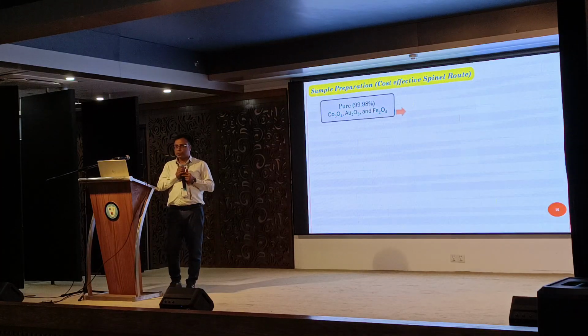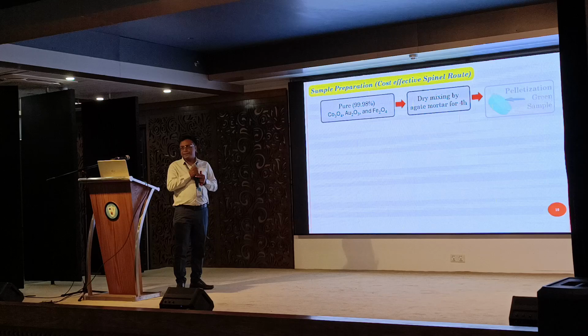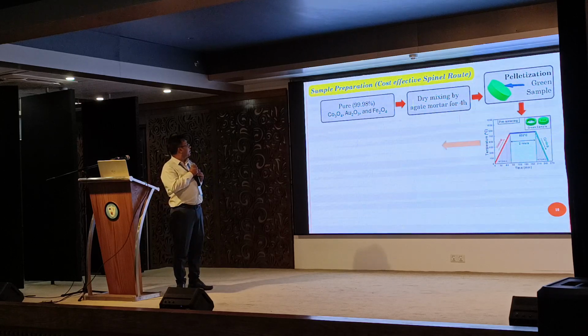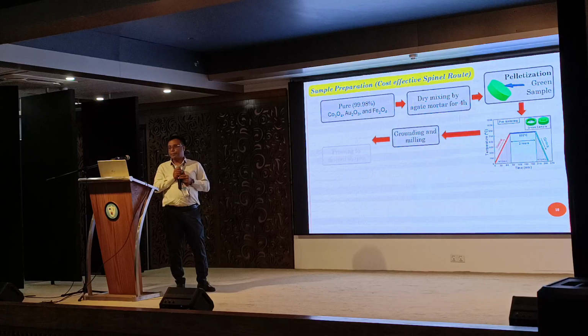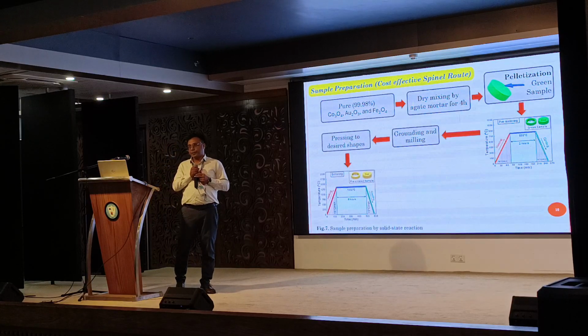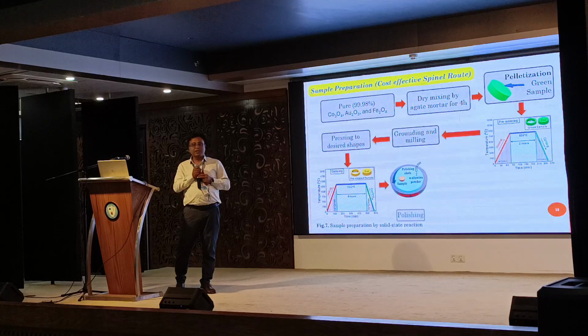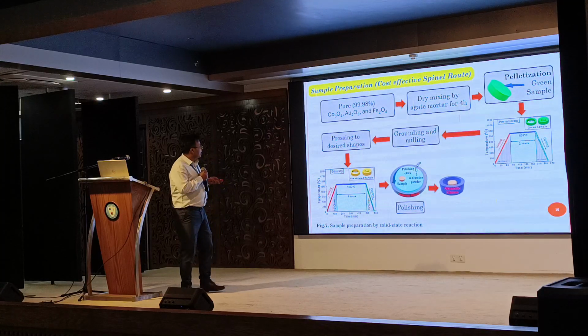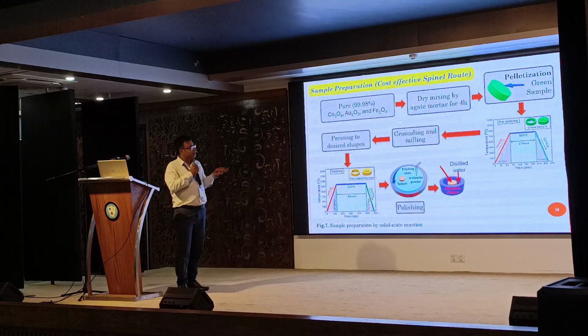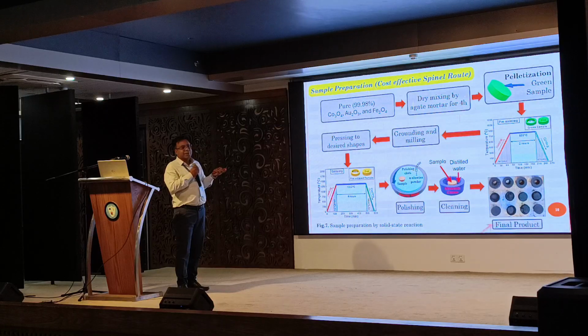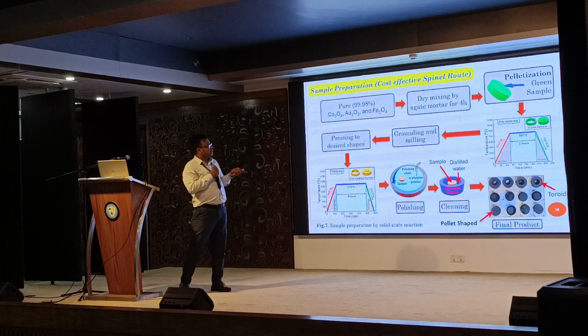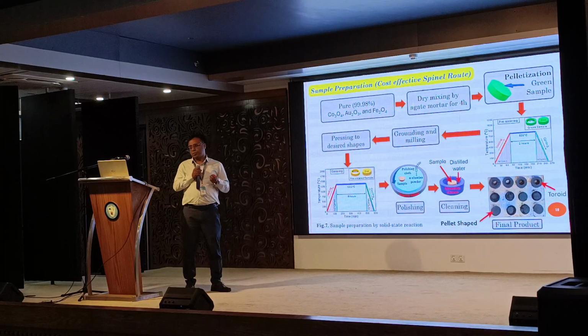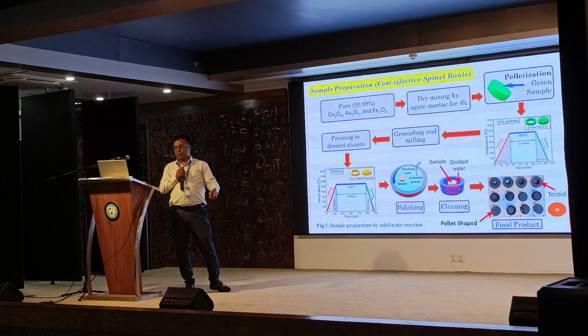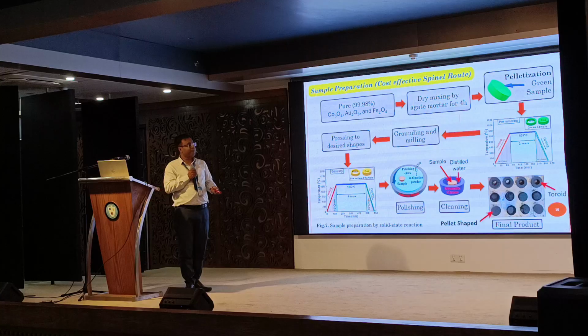So we followed some other route that is cost effective and a very easy method. That is the solid state reaction method. We implemented a double sintering technique: one is pre-sintering, then the final sintering. Here the raw materials are oxide materials, and these oxides we dry mixed for 4 hours in an agate mortar. After that we made pellets. For this we took help from another source, but in the future we will also have it inside our lab.